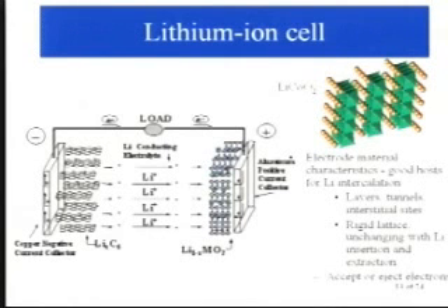Now I'll just go into lithium-ion cells. And how a lithium-ion battery works is lithium ions are shuttled back and forth between the anode and the cathode. And usually this schematic here shows a discharge where the lithium ions come back out of the anode, which is a carbonaceous material, typically graphites of different morphologies. There was a list of different carbons presented earlier, and turbostratic carbons have been of interest in this too. That's just an aside. But how it works is the lithium ions go back and forth between these two materials, and so you need an electrolyte, lithium-containing electrolyte.